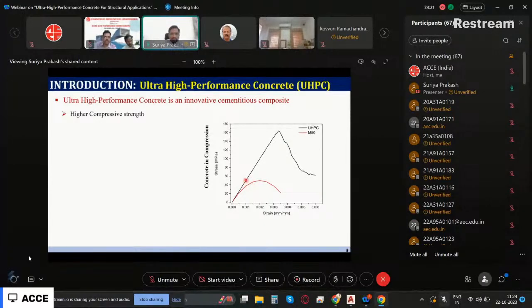And the elastic modulus, which we call the stiffness of the material, is also going to be higher. And we know that Ec is 5,000 square root of fck as per your IS 456. Higher the compressive strength, higher will be your elastic modulus. So the moment I increase the compressive strength, all other parameters also increase. Tensile strength increases, shear strength increases, and so on. Right? So this is the advantage.